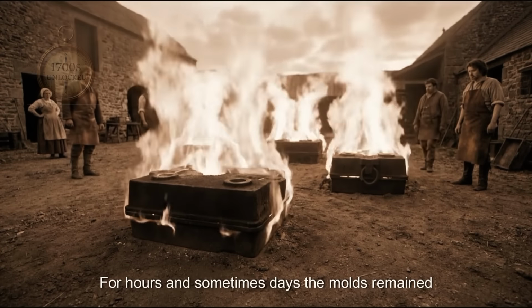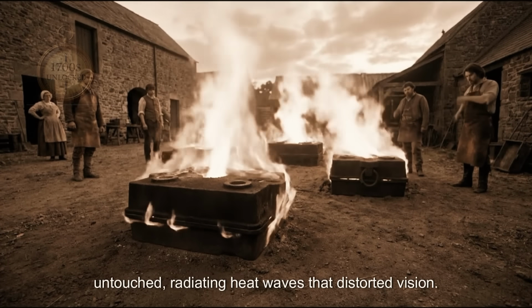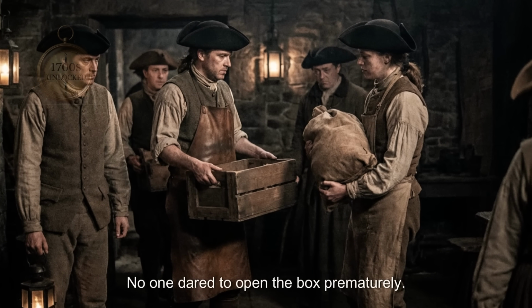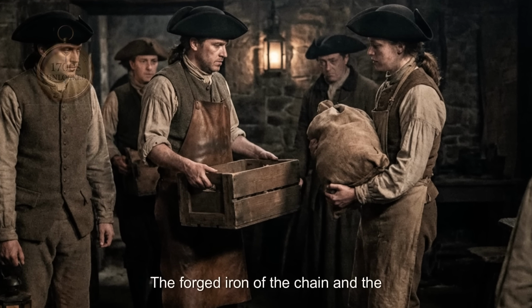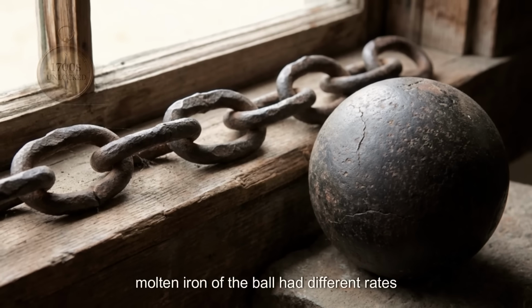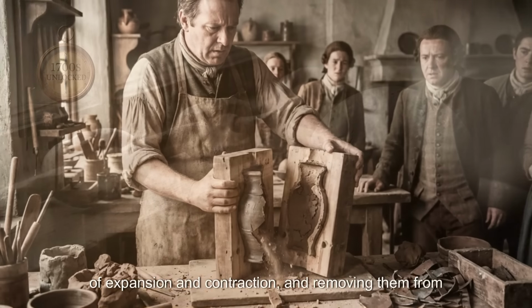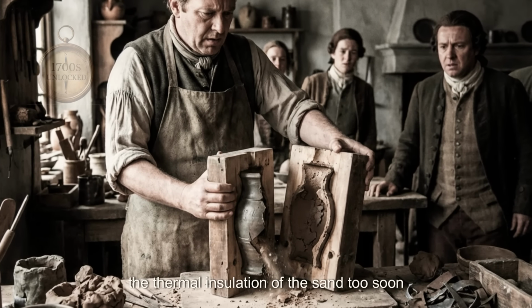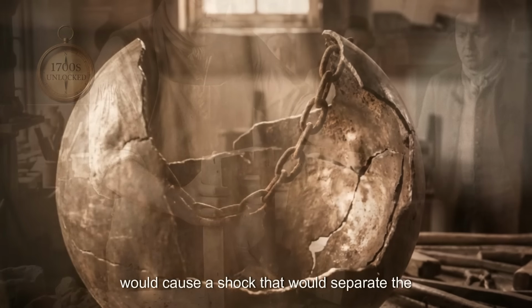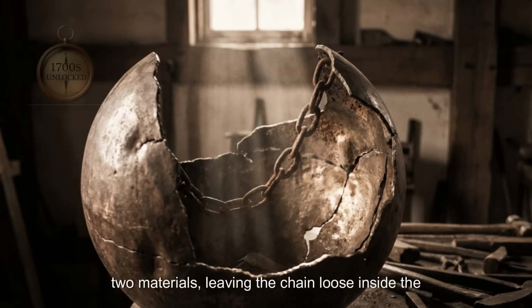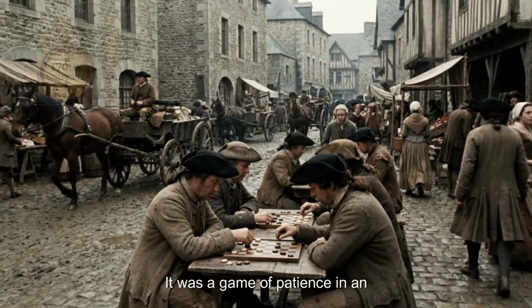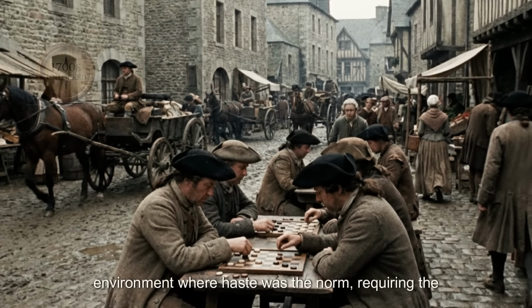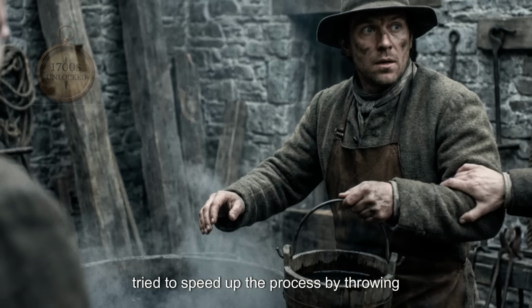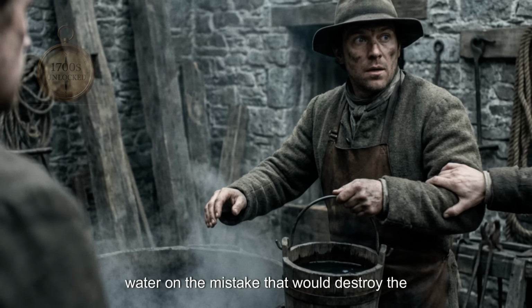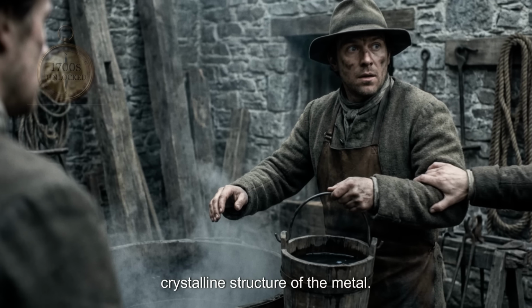For hours and sometimes days, the molds remained untouched, radiating heat waves that distorted vision. No one dared to open the box prematurely. The forged iron of the chain and the molten iron of the ball had different rates of expansion and contraction, and removing them from the thermal insulation of the sand too soon would cause a shock that would separate the two materials, leaving the chain loose inside the ball. It was a game of patience in an environment where haste was the norm, requiring the foreman to watch so that no anxious worker tried to speed up the process by throwing water on the molds, a rookie mistake that would destroy the crystalline structure of the metal.